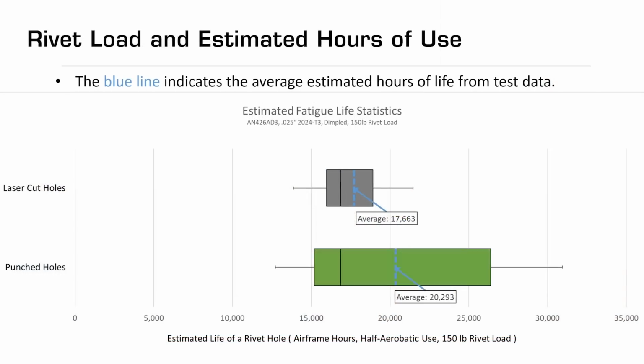So this chart explains a large group of data and is comparing laser cut to punched holes. This is a statistical tool. It will highlight the lows, highs, and the variability of the spread of the data. This specifically is the flush 3/32 rivet in a 0.025-inch thick aluminum. This is our most common rivet hole configuration, especially in these laser cut components. And what we're doing here is refining the data to predict the onset of fatigue cracking in a single hole.